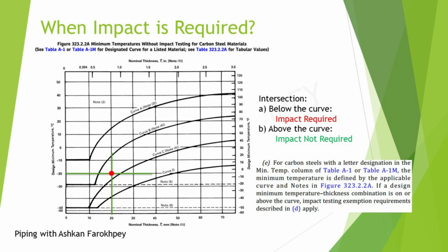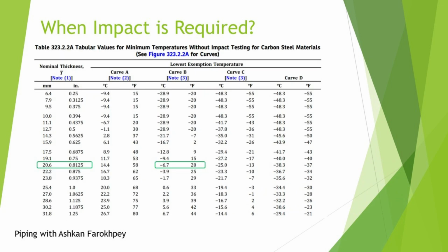Don't forget that each diagram in ASME B31.3 has a tabular value table for giving you the exact numbers and to prevent mistakes. Here in our case, as an example, when the material's thickness is around 20 millimeters, the minimum design temperature that ASTM A106 grade A can be used without impact testing is -6.7 degrees centigrade or 20 degrees Fahrenheit. Below that, the material requires an impact testing based on the details mentioned in Table 323.2.2.